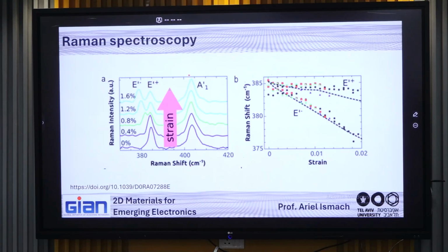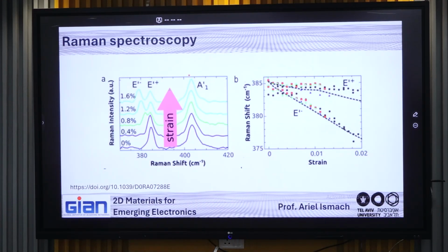Yes, but think about that. You have hexagons, right? So you now have elongated hexagons. So you have two main directions: the in-axis direction along the strain and the perpendicular one, which are very different in distance. And that impacts the vibration in these directions. So those are known as A and E peaks.